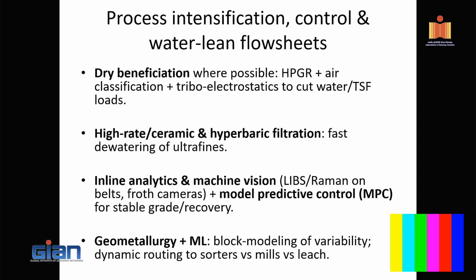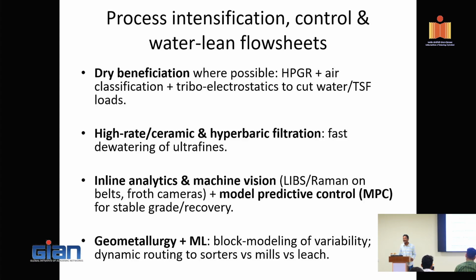Yeah, so I think that's one area where Coal India is still watching for a better option at commercial level. Pilot scale research is already done, like IMMT Bhubaneswar long back, using an air dense medium separator. But I think further TRL 6 and above, they could not take forward. Basically, recoveries are quite low compared to the dense medium wet route and flotation. Otherwise, you can use a combination. For example, HPGR anyway is quite good in terms of reducing effective sizes. But then you can also adopt air classification and triboelectric separators for a certain range of particles that you can target. But as an integrated module, it is not being attempted quite straightforwardly.